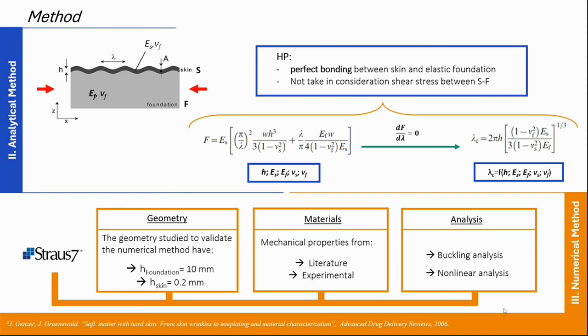As can be seen, when the skin thickness and the ratio of the two elastic moduli are low, the critical wavelength is small, but when these terms are high, the wavelength significantly increases.